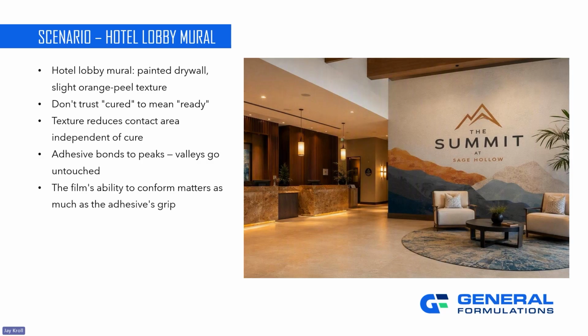But that's the other part, and it's the trap that catches a lot of people more than texture does: smooth, fresh, low VOC paint. It looks and feels like it's ready, right? It's dry to the touch. But the thing with the low VOC and zero VOC paints is that the chemistry is active and curing long after it feels dry to the touch. Don't ever just trust feel alone. You need to verify the cure time, pay attention to the texture, and we'll talk about this in a little bit. Patch test the actual wall before you let the job move forward.